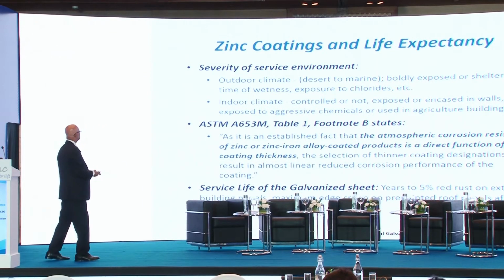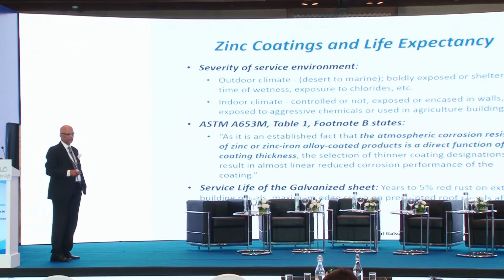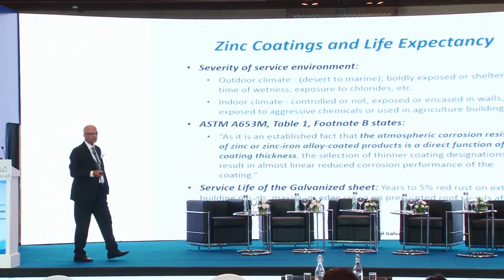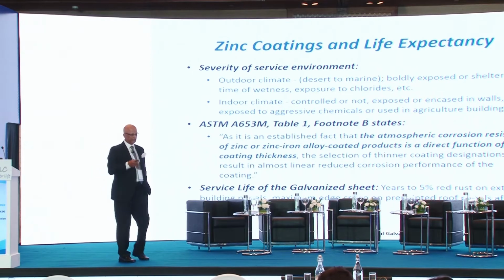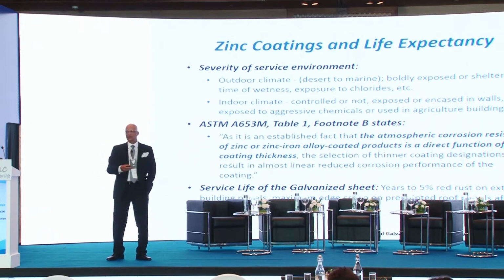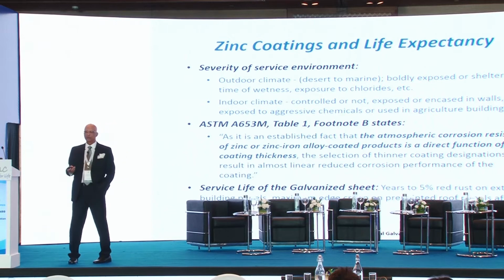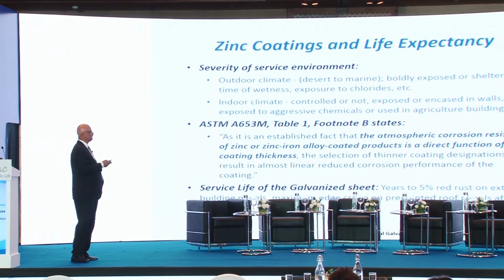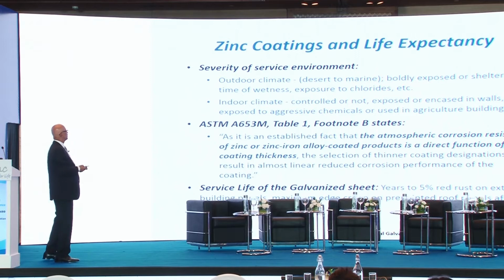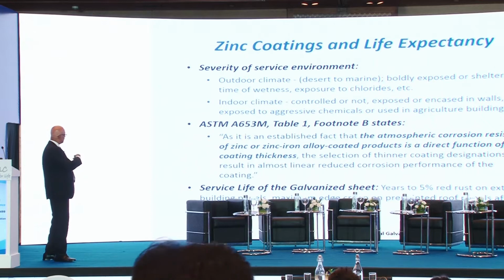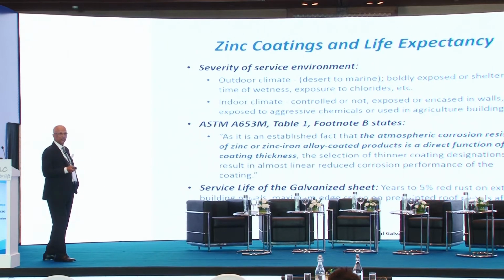So life expectancy of the zinc coating basically depends on the severity of the environment, right? If the outdoor climate is severe, you can expect more severe corrosion. If the product is exposed boldly to the atmosphere or sheltered, it'll affect it. Time of wetness, the exposure to chlorides, seaborne salts. If it's indoor, obviously it's not going to be as severe unless the manufacturing building is producing aggressive fumes and so on.